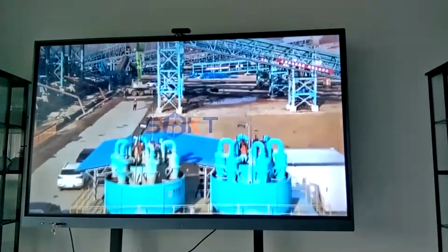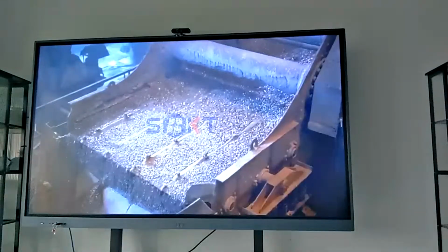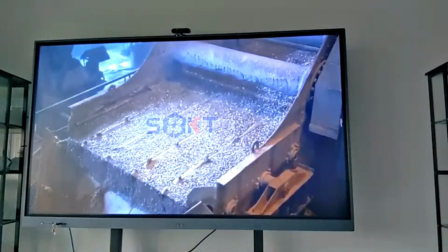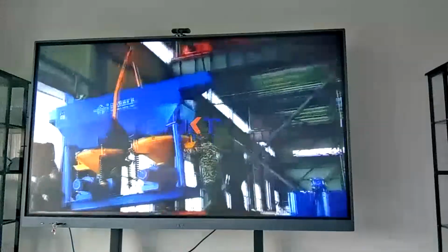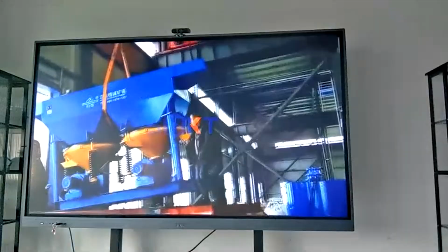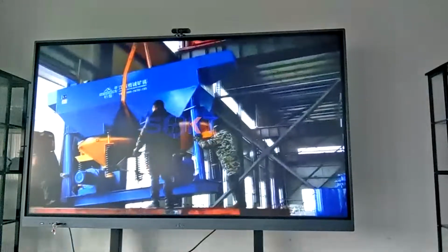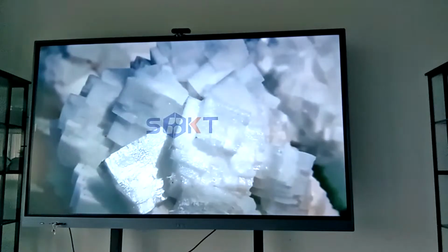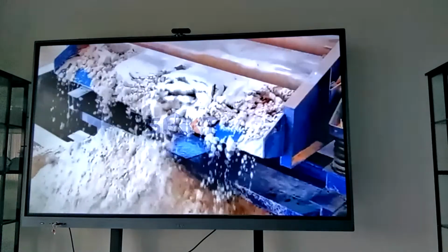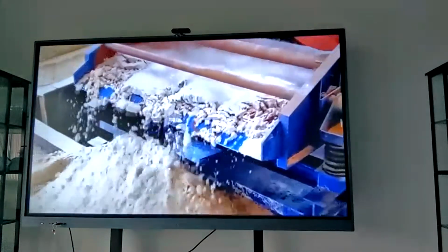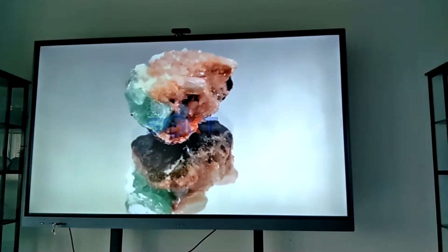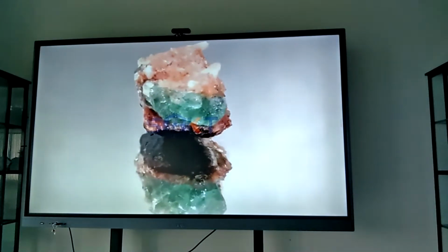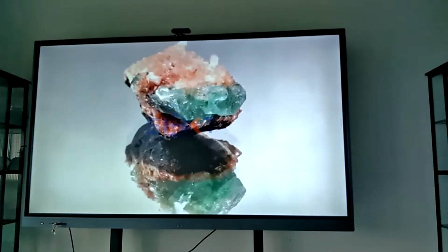This is the most economical option. Crush to a certain particle size, or even without crushing, then directly pile up on the heap leach pad. Low grade, large scale, good permeability: high heap leaching.